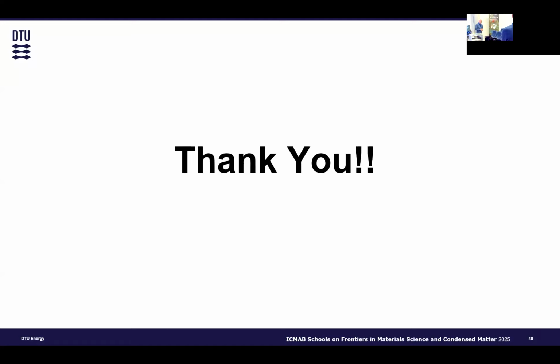Thanks, Nini, for this inspiring presentation. I have a couple of questions. One regarding the beginning, where you mentioned some 2DEGs that you formed using STO and LAO on top. In the continuous film, it turns out that the mobility was very high, but in the small flakes, the mobility was very low, about 25, something like that, I think. And you mentioned that you guess that could be due to the polymer that you have used and residuals of the polymer. I really don't understand how the polymer can modify the mobility of the 2DEG. I mean, the 2DEG is the 2DEG. Why does the mobility depend on the polymer? This is one question.